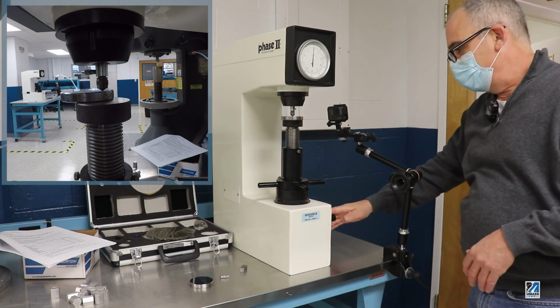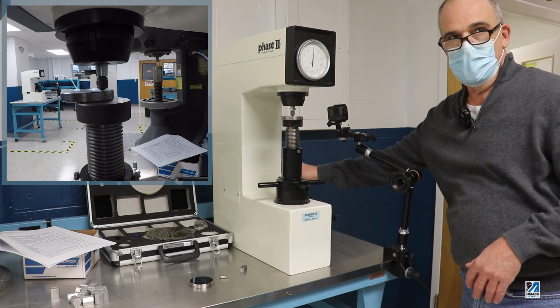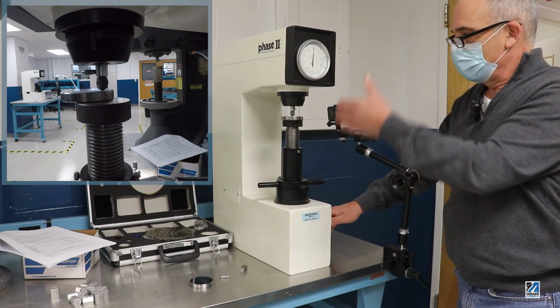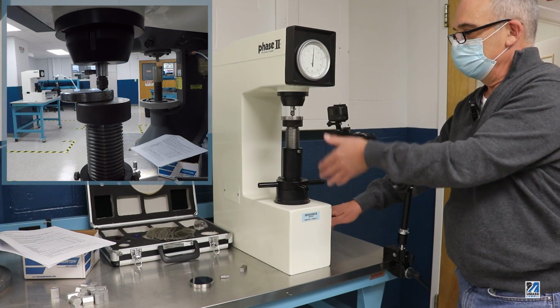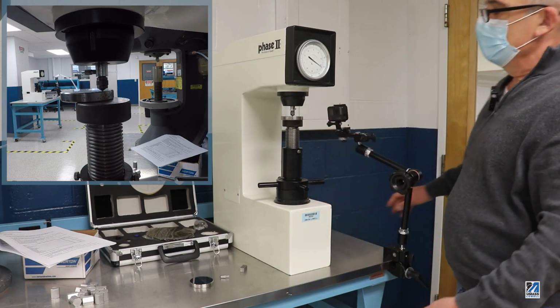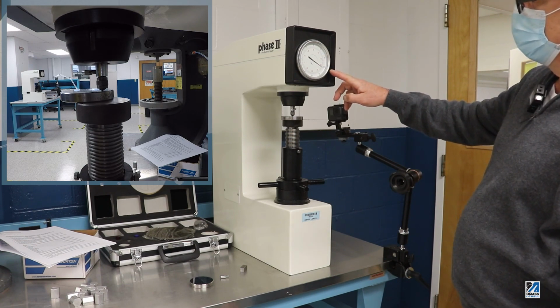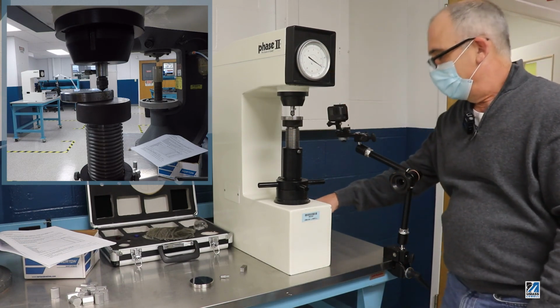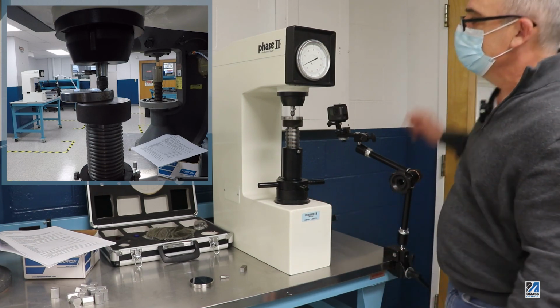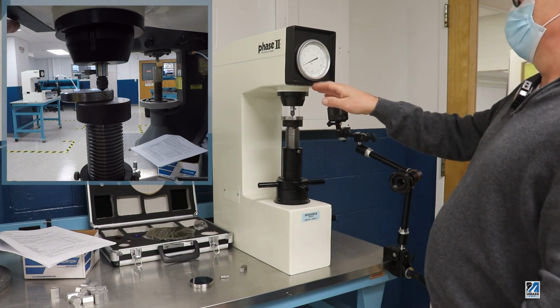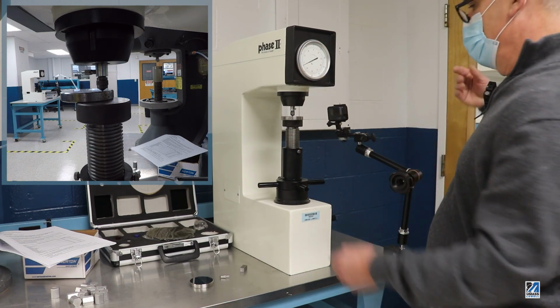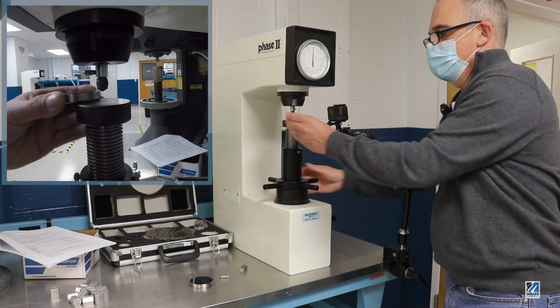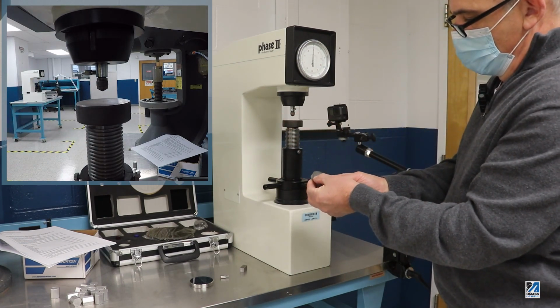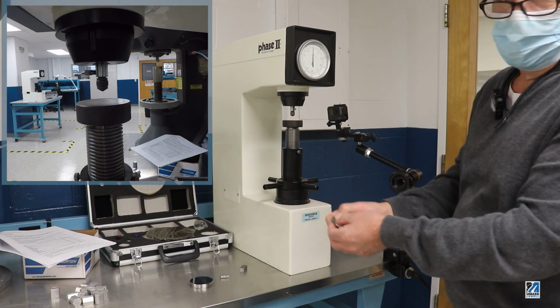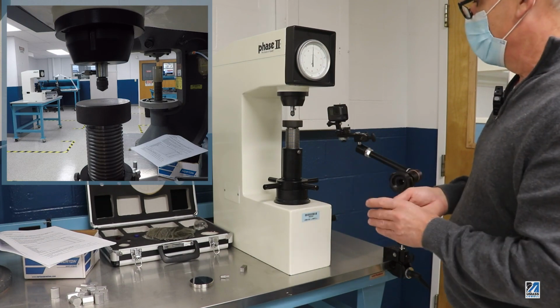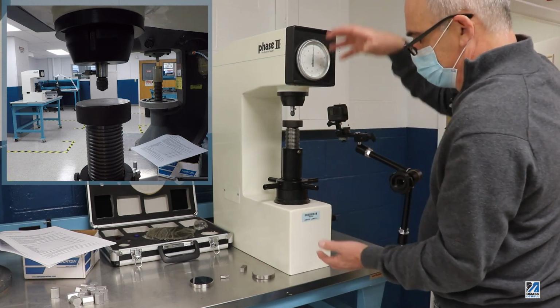And at this time, I've already preset my major load at 980. And I'll go ahead and apply that load now. So that's going to drop weight and force the material into the indenter. What I'll do is I'll wait for the needle to stabilize, and then I'll take the load back off, and we should be able to read the Rockwell B of approximately 97. I'll unload the sample with the minor load. And this one had a Rockwell B of approximately 95.8 or 96, so we're essentially on. So that's a quick check of the Rockwell B, whether or not this is set up properly.